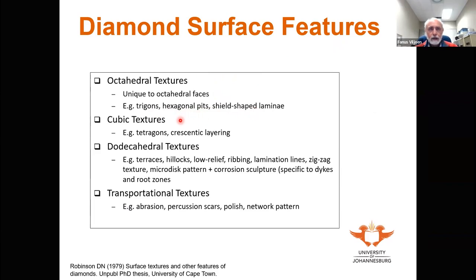If, on the other hand, you look down the cubic crystallographic direction of diamond, you see things like tetragons and crescentic layering, which is again unique to the cubic direction. On the other hand, if you look at dodecahedral diamonds, you see a whole horde of surface textures. Dodecahedral diamonds obviously are the more resorbed form of the primary crystallization forms. And so here, there is no uniqueness in terms of crystallographic direction. What you see is things like terraces, hillocks, low relief, ribbing, and so on.